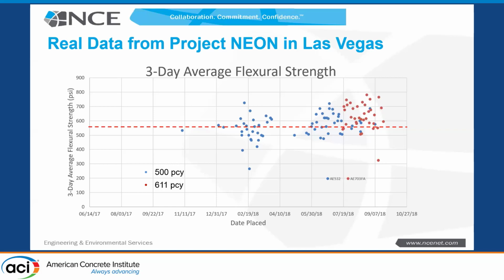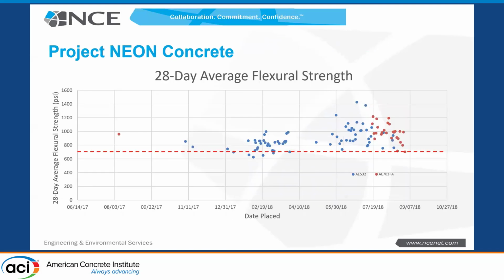But if you look at this data, even at 3 days, there's not a lot of difference, right? Factoring in the fact that this was February, which even in Vegas is cold compared to later. If you look at the 28-day averages, we actually had, on average, higher strengths with 500 pounds per cubic yard than we had with the 611. So this can be done and it should be done, especially on airfields.